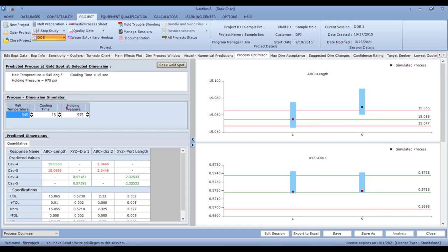You might say 15 seconds is too long — I want to run this mold as fast as possible. Drop the cooling time to eight seconds since we know you can still make good parts at that setting. My preferred process is now 545°F, eight seconds, and 975 PSI. I always select a point closer to the center of the process window for pressures, since pressures cause defects like flash and short shots. The low is 800 and the high is 1,200, so 975 PSI is a good center.